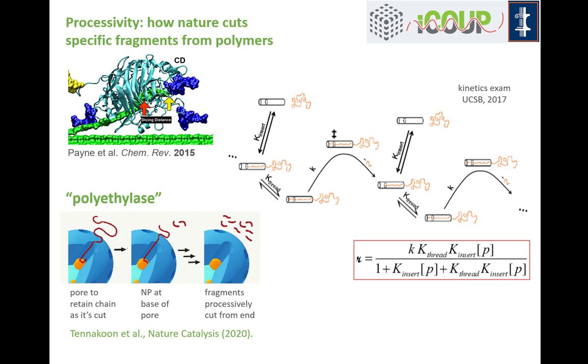This is a processive mechanism because the substrate doesn't adsorb, get cut, and then desorb. Instead it adsorbs, gets cut again and again and again, until the substrate polymer chain is gone and then the pore is empty and ready to take in a new substrate polymer.